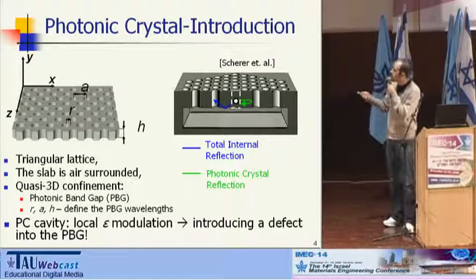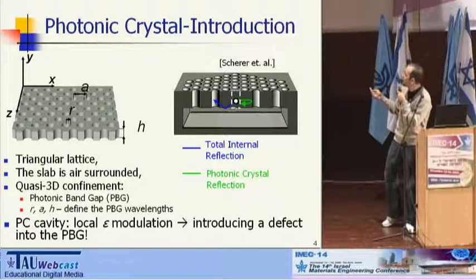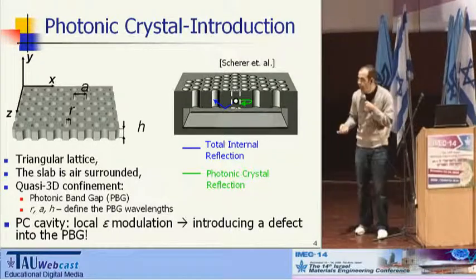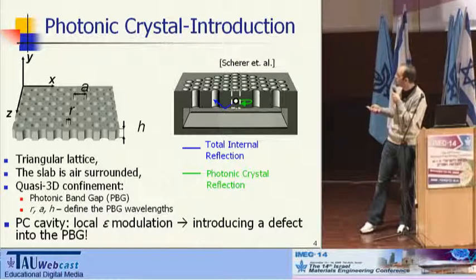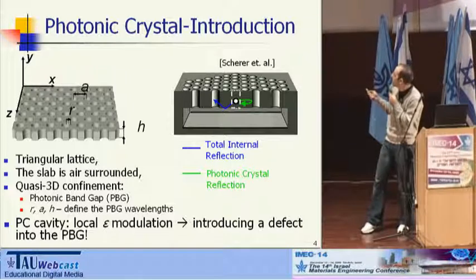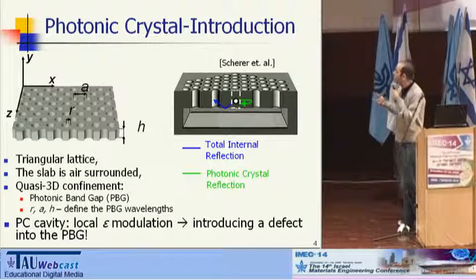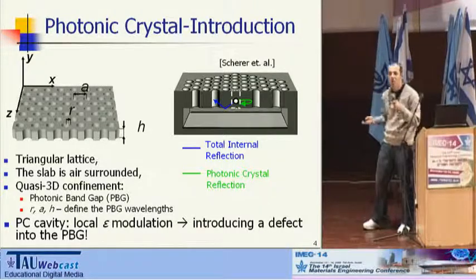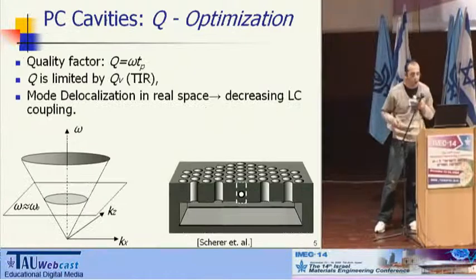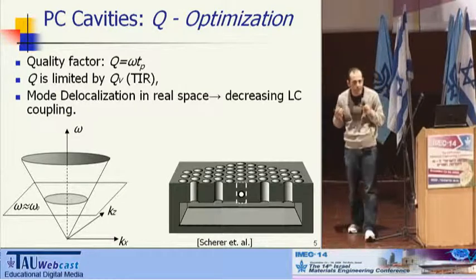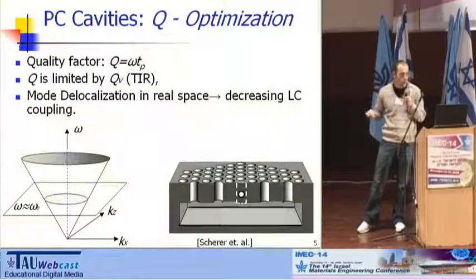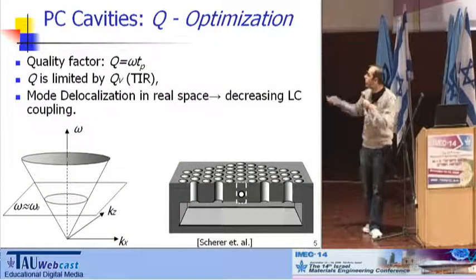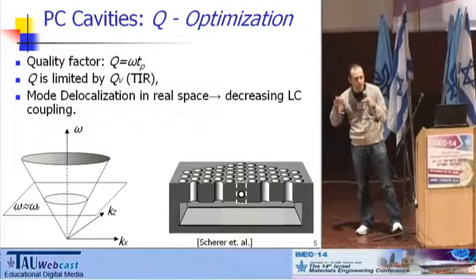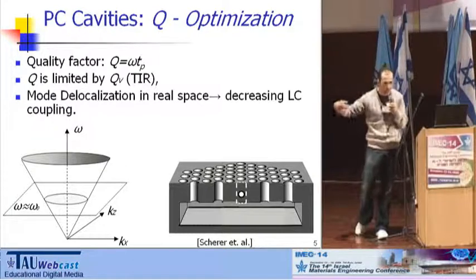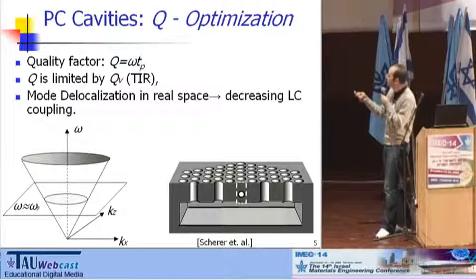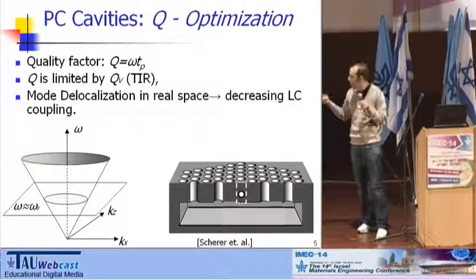Now, we would like to form a photonic crystal cavity, which is actually a light trap, where the light will be trapped as long as we can, and this cavity is formed by local dielectric constant modulation, which introduces an effective defect into the bandgap. The light is then localized by mainly two mechanisms, total internal reflection and photonic crystal confinement, which is actually the Bragg confinement. So, to form a high-Q cavity, the cavity where the light decay is the slowest, we've got to limit our losses. Our lateral losses along this membrane can be ultimately limited by adding additional photonic crystal layers, while our vertical losses, which are defined by total internal reflection, will define the quality factor of this nanocavity.